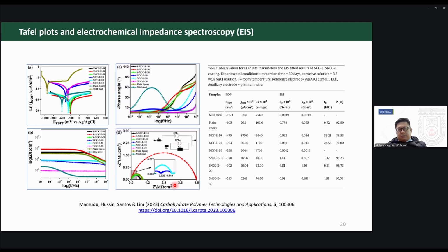But if you have two, you will see that there are actually multiple, at least two diffusion pathways for the electrochemical reaction, and that sometimes indicates two corrosion reactions happening. When you normally work in maritime, in sodium chloride solution, you can have two, because one is the electrochemical reaction of the hydroxide ions, and the other one is to do with the chloride ions. So if you see two, you know that actually there's chloride species penetrating your coating.